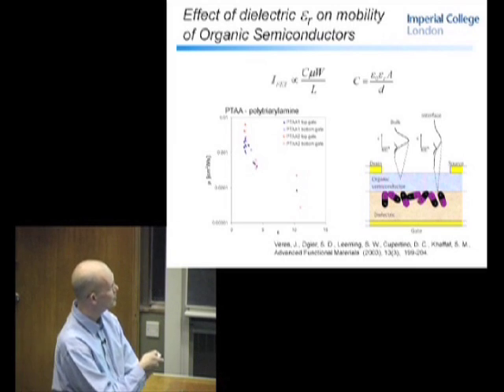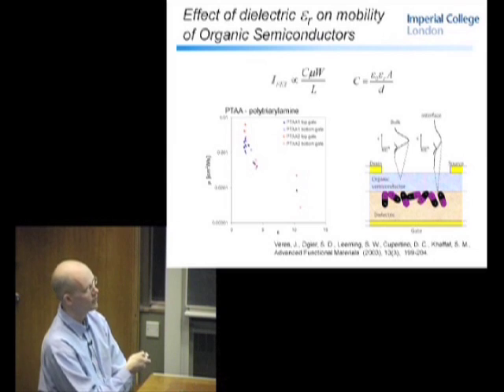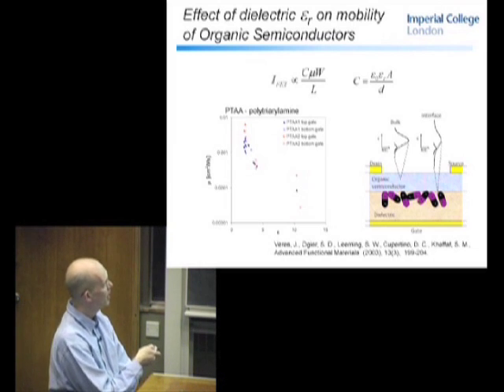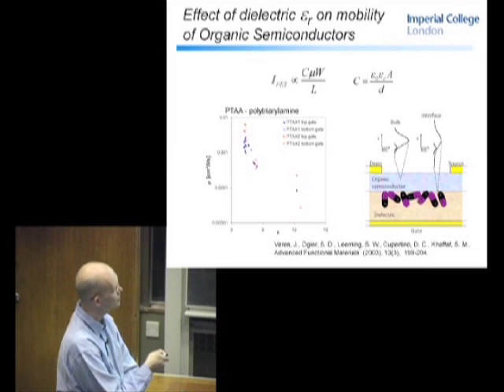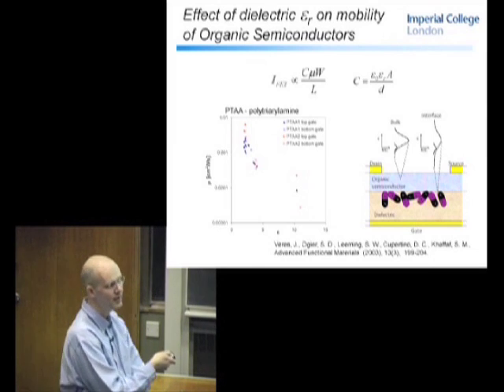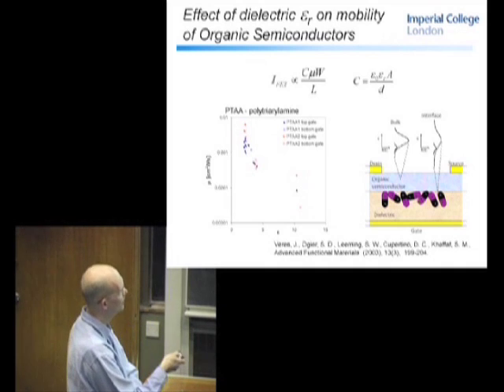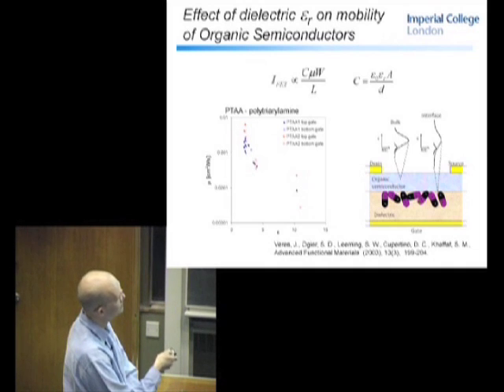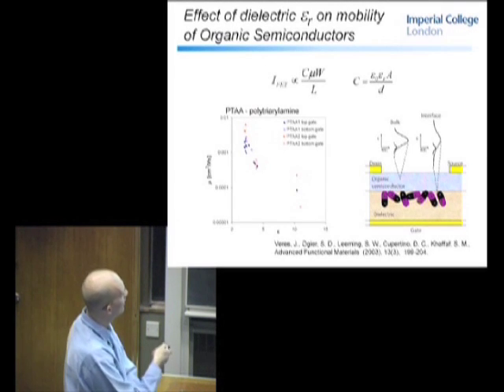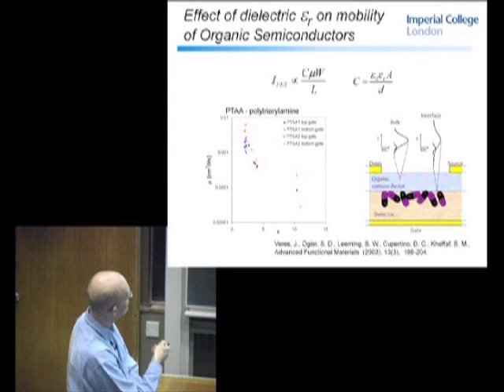And what they proposed was that you need low-K dielectrics for high-performance organic semiconductors. They made an argument on the basis of energetic disorder at the interface. If you have a high K, you have high polarity at this interface, and what they're showing here is the density of states, at the bulk and at the interface, broadened by this dipole effect, making quite a convincing case. In the case of polytriarylamine, this is mobility, and this is the dielectric constant of the dielectric layer.